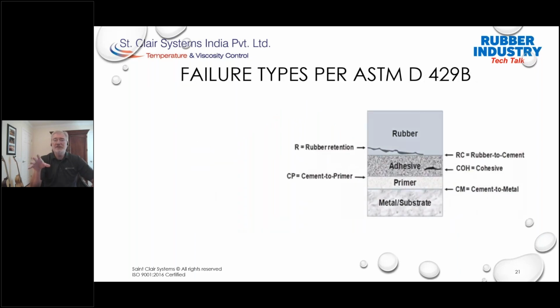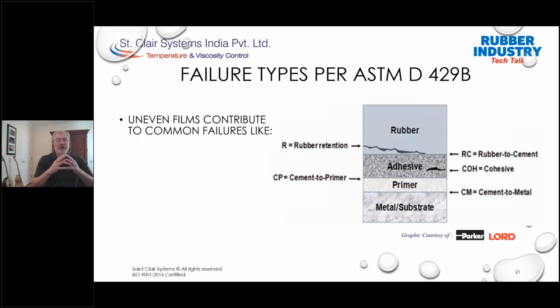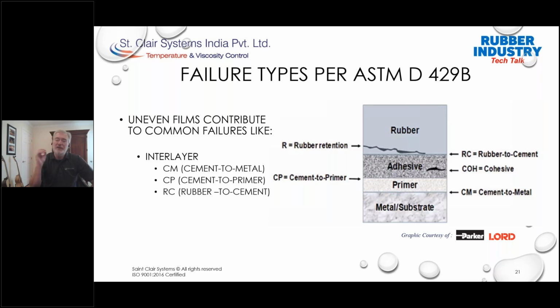Now, these things all add up to create defects, okay? And what defects do we attribute with these temperature-induced changes in the Chemlok and primer viscosity? And they're all the same ones that you're used to. First, there's the interlayer failures. These are the result of poor bonding between the substrate and the primer and the Chemlok, and the Chemlok and the rubber itself. So there's three different transitions there where these failures can occur.